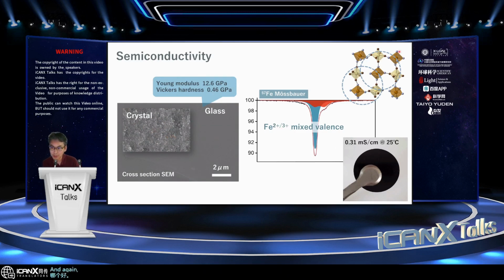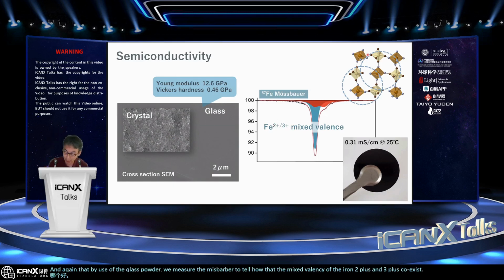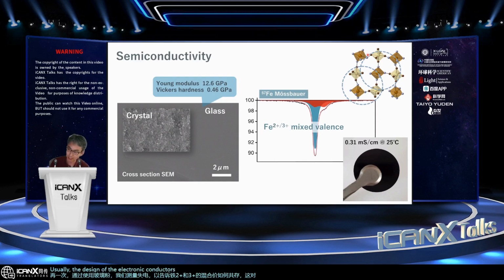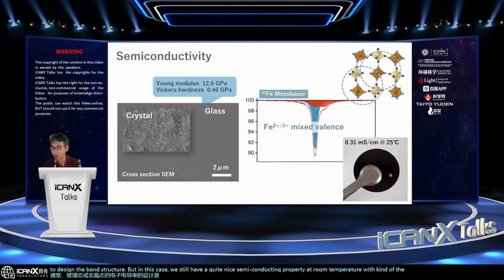And again, by use of the glass powder, we measured the Mössbauer to tell how the mixed valency of iron 2+ and 3+ coexist, which is very important to have electronic conductivity in the glass. Usually, designing electronic conductivity in the glassy or amorphous state is very difficult because of the band structure. But in this case, we still have a quite nice semiconducting property at room temperature, with a very nice monolithic form.